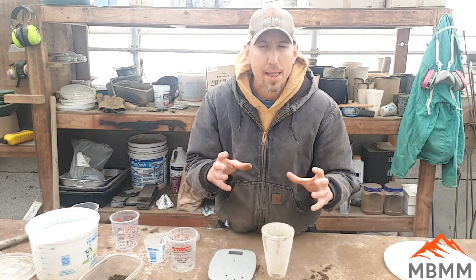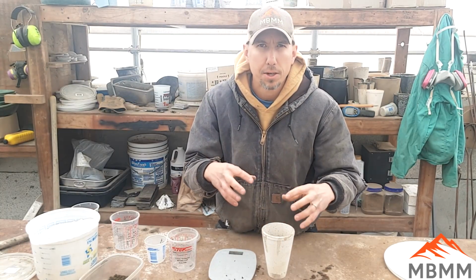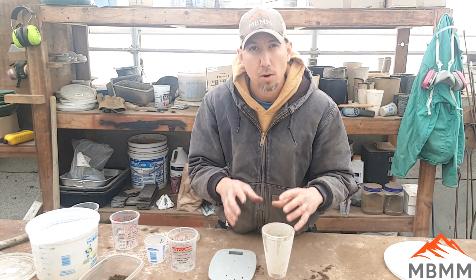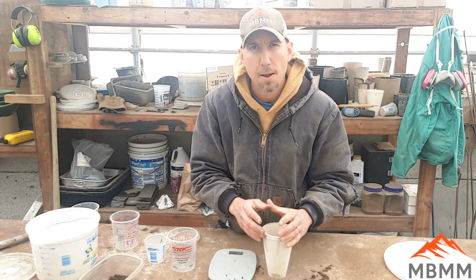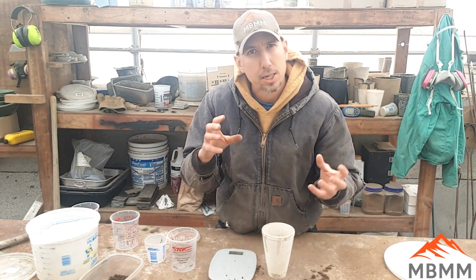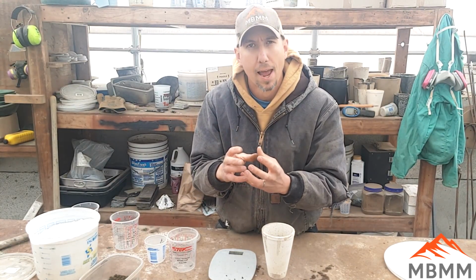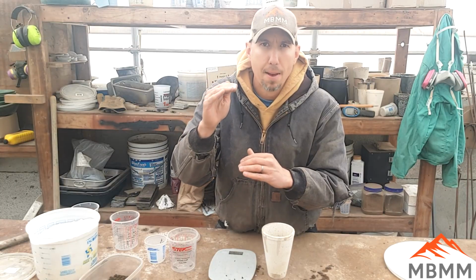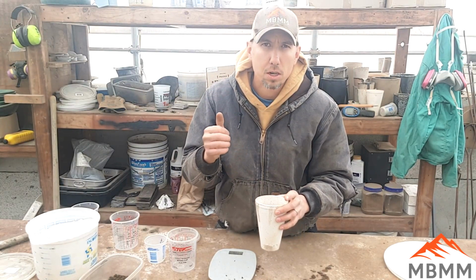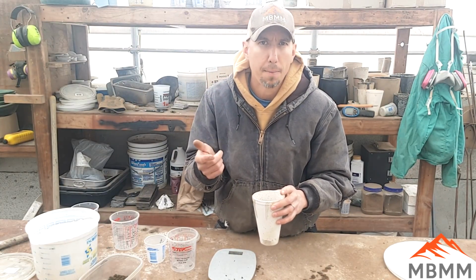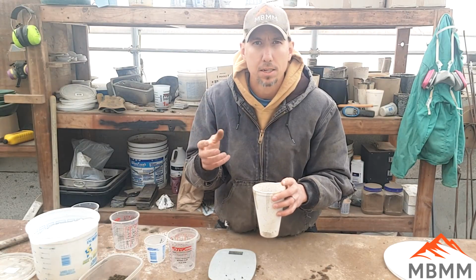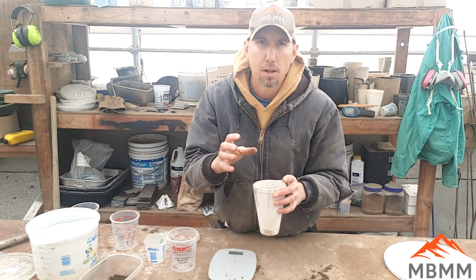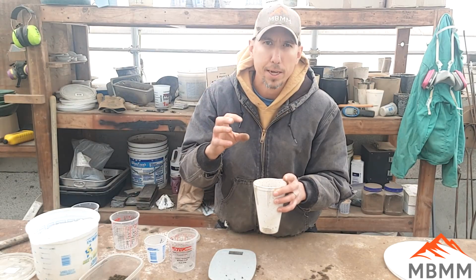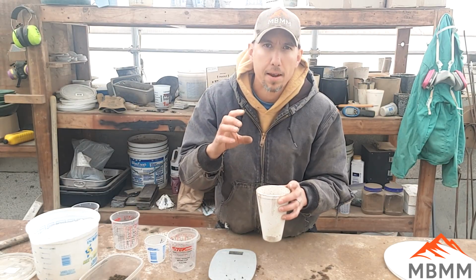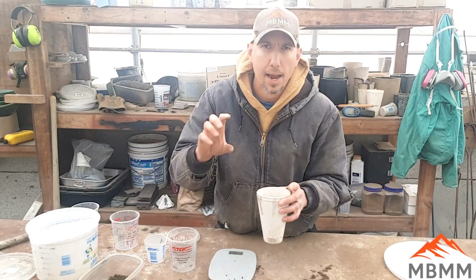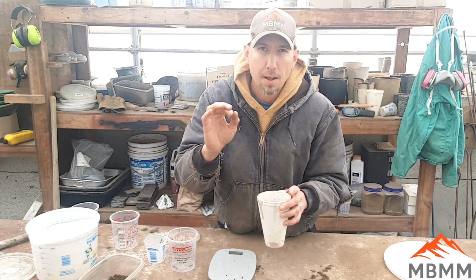And when that forms, because we have such a basic slag from our soda ash, we put a lot of soda ash in there, that iron sulfide is actually going to get dissolved up into that slag, and there won't be any matte. And so if there's galena or lead, copper, arsenic, any of that stuff, we're going to reduce all that to metal. We're going to have all that replaced with iron sulfide, and then the iron sulfide is going to get dissolved in the slag, and we'll have a little metal button at the bottom if there's enough.